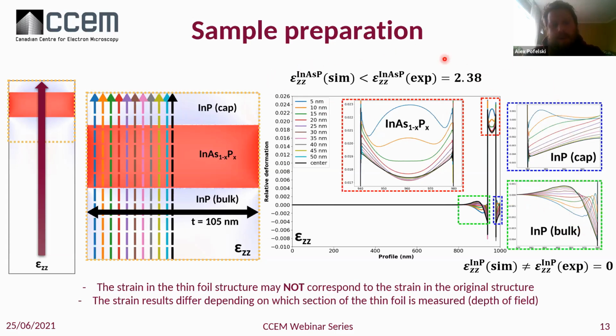So already, from our expected 2.4%, in general we will get something that is lower. And where it's supposed to be 0, we don't have a 0. This is very important to keep in mind, because when we do the strain characterization method and we would like to compare to simulation, it's good practice to add this strain relaxation phenomenon, because if you just go towards simple models, you're going to pretty often be disappointed by the mismatch.